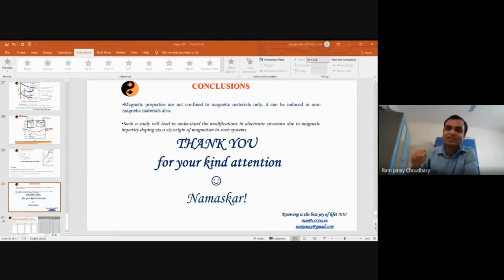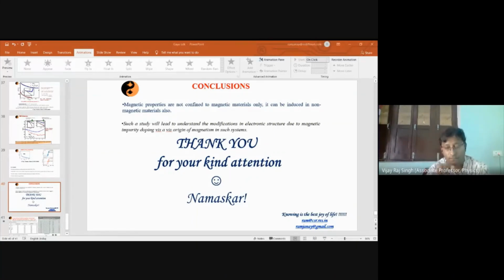Now, in the indirect exchange interactions, you have a wide range of interactions possible, like double exchange interaction, RKKY interaction, then you have the Kondo interaction also. Kondo interaction is not actually a magnetic exchange, but it gives rise to some kind of scattering of the charge carriers at very low temperature. But remember, to understand double exchange interaction, your magnetic ion should be present in heterovalency. Only then will you have double exchange. So you have to understand the charge state of the magnetic ions present in your material. All these things you can do to get an idea of what kind of ions are there and what the possible exchange interactions are. But to get the absolute answer, I think theory is the best way to go.